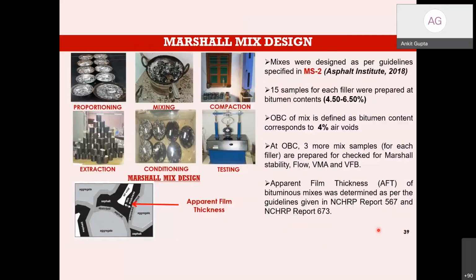This is a very conventional Marshall mix design. Those who are not from the pavement side, they do not need to worry about it. And those who are from the pavement side, they must be having a good idea of the Marshall mix design. So we did as per the conventional MS2 method, the MS2 codal guidelines. 15 samples were prepared for bitumen content varying from 4.5, 5, 5.5, 6 and 6.5. The optimum bitumen content of the mix is defined at the bitumen content which corresponds to 4% air voids.